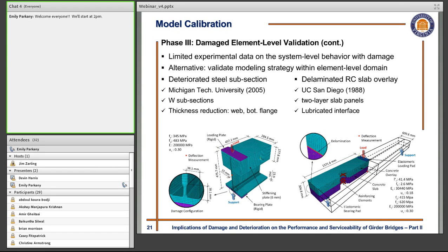The first one was a series of experimental investigations on deteriorated steel subsections performed at Michigan Tech back in 2005, where they had these W sections and they reduced the thickness of the bottom portion of the web and the bottom flange to simulate the effect of corrosion. And again, they had a bunch of models, and between those we selected the one that you can see in this figure. We created the numerical models based on the geometric and material properties they provided in the test report.